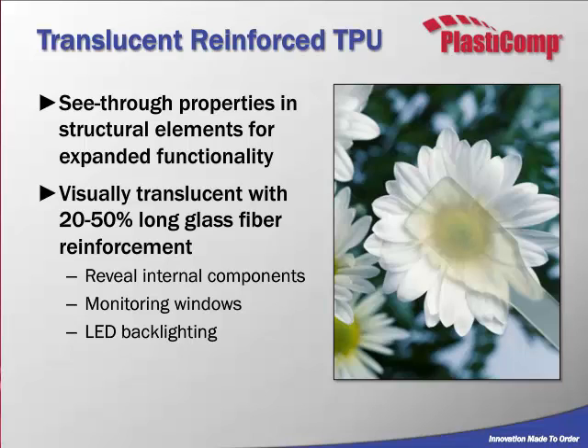This product is a transparent, contact transparent, translucent material that is structural. So we were able to load this material up with glass fiber from 20% to 50% by weight, and still maintain some contact transparency. So you've got a structural component here that would give you the ability to see through if you had any types of revealing internal components that may need maintenance from time to time. So it gives you the ability to have a monitoring window that has some structural integrity.